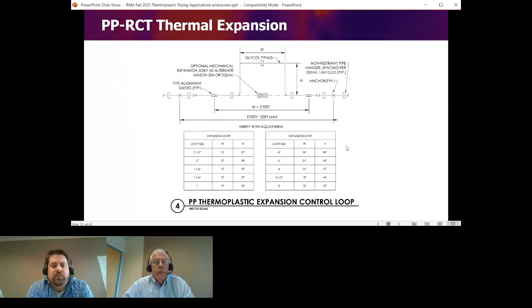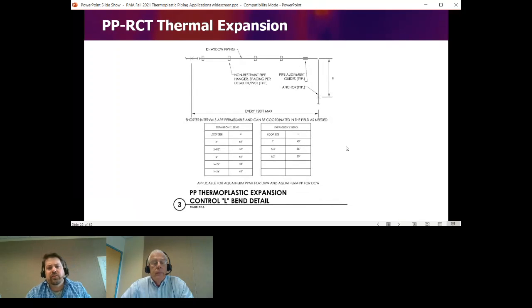In buildings and even in site utility distribution, you still have to control expansion growth. And you can apply similar methods that you would use for steel and copper pipe. For example, maybe every 150 feet of linear pipe, standard practice is to do expansion loops, where you basically put an anchor at the start and the end, put some guides in the intermediate locations, and put a big U-bend in, so it can expand and contract. You can also use expansion joints as an alternative. L-bends are also an option, similarly using different mechanical devices with anchors and guides.